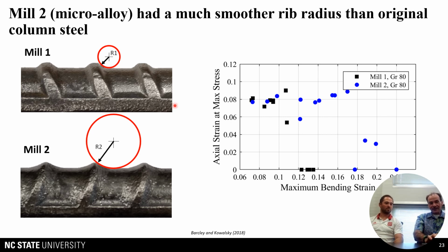And then you saw that in these tests. So you could see it in mill 1. Mill 1, I think, was the one that we did the column test with. Yeah. And we thought, well, what influences this bending strain? Is it the actual metallurgy of it? Is it quench and self-temper? Is it microalloyed? Or is it the geometry of the actual ribs? Or some combination of the two, which is probably the case.